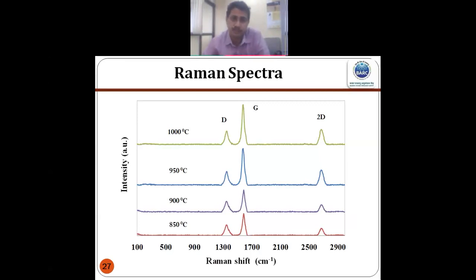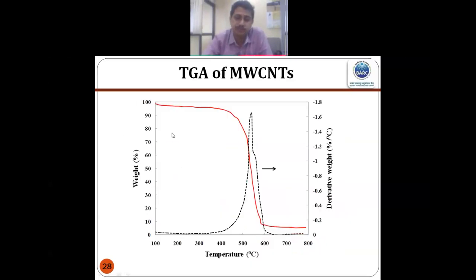The first thing is we should get a Raman spectra. Raman spectroscopy is an easy and very useful characterization technique for carbon nanotubes. There are typically 3 peaks, D, G and 2D. G corresponds to the graphitic type of vibration, D is the disordered nature of vibration, and 2D is an overtone of D. Generally, if it is multi-walled carbon nanotube, we get a high value of D. For single wall nanotube, G is very high and D is low. And in single wall nanotube, we get another peak called RBM, which I will show next. Here I am showing how these three peaks vary with respect to different temperature.